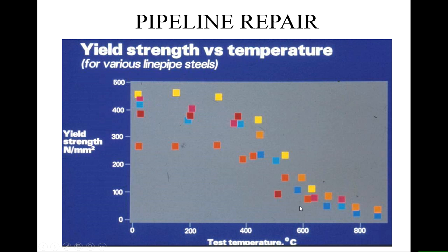And this is the yield strength, so this is when plastic deformation starts. By the time you get up to about 600 degrees C, all of those steels are very similar in performance and the strength is not very good. In fact, mechanical properties of many constructional steels at 900 degrees C are not too far different from the mechanical properties of butter. So they're not going to withstand much in the way of strength. That means that when welding, you're heating up the material. Not only are you making it hot and the possibility of liquid metal formation that can cause breaching of the weld, but you also have a very soft material which can be blown up by the internal gas pressure, a bit like a balloon. I showed you a picture of that in the previous case. So we want to try and minimize the temperature that the material around the weld sees.